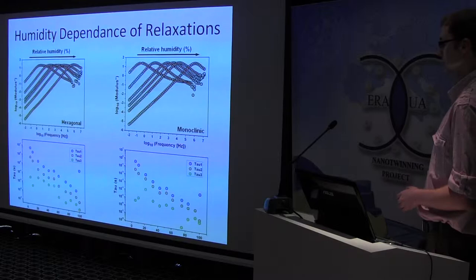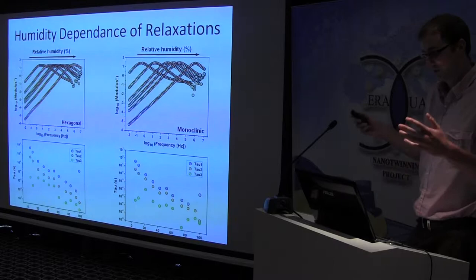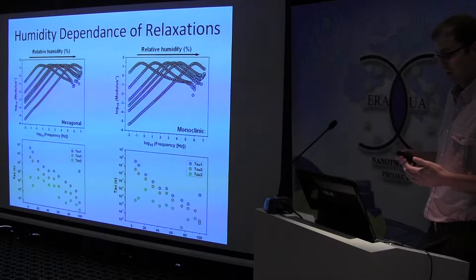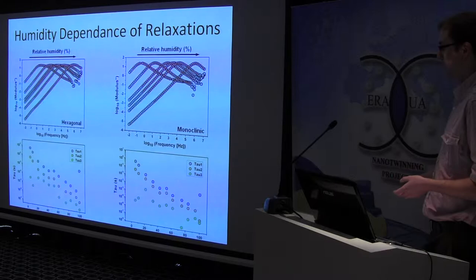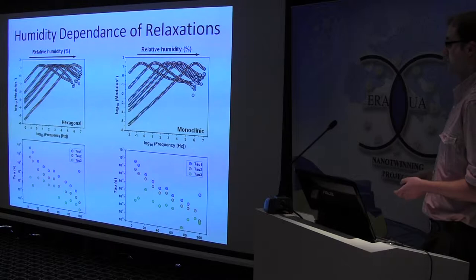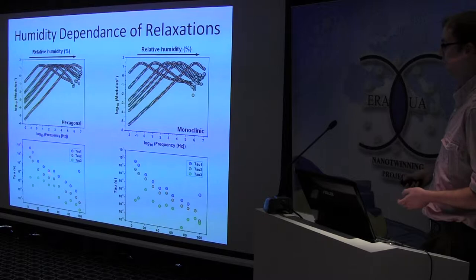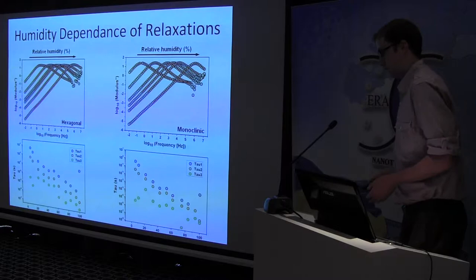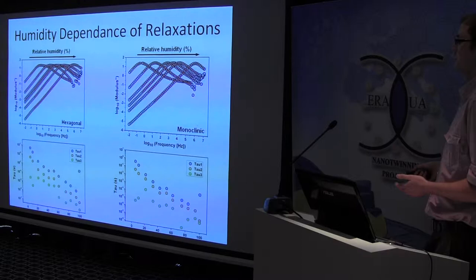And there is a question what processes could cause these relaxations. And we know that our samples don't contain any dipoles and we can also see that the relaxation times depend on the relative humidity and the conduction of the material. So we suggest that these relaxations can be referred to interfacial polarization in the sample.